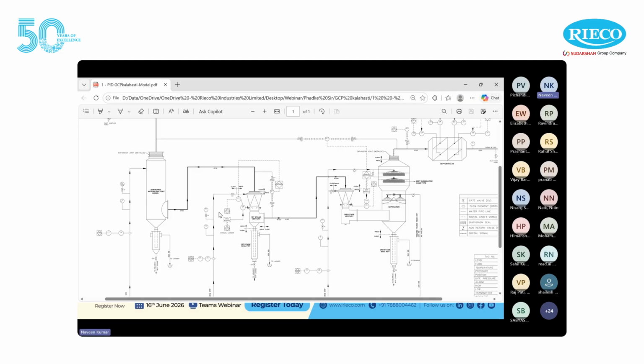Now, this hot gas coming out of the furnace is utilized essentially for hot blast stoves, boilers, sinter plants, coke ovens, and captive power plants. The typical pollutants we have to deal with in a gas cleaning plant are basically dust, carbon monoxide, sulfur dioxide to an extent, NOx, and carbon dioxide, which is about 1.5 to 2 tons per ton of hot metal. If we look at the work zone hazards this plant creates, you have CO leaks at times, and then there is dust, heat stress, and H2S traces to deal with.